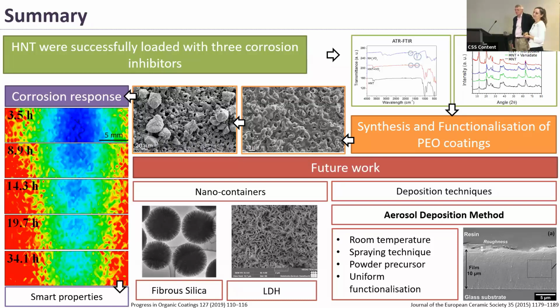Thanks, Bea. Very interesting talk. I noticed that your functionalization treatment is effectively a simple immersion treatment. How do you know that when you put them in the corroding solution, these encapsulated inhibitors don't just float away from the surface? They are quite well adhered, but of course they are physically adhered. That could happen, but I don't think that happens because I did a corrosion test and we could observe this self-healing behavior, which suggests that they remain sealing the pores. But yes, it could happen. Thanks.